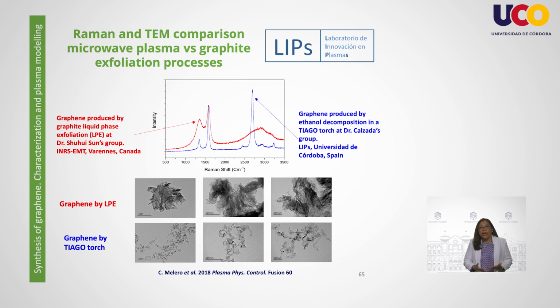Now, in this slide, we can observe the Raman spectrum and TEM analysis of the graphene produced by graphite exfoliation versus the graphene produced from plasma. Graphene from exfoliation presents a higher number of defects and more layers. The morphology is also very different. The graphene from plasma produces flakes with a highly crystalline turbostratic structure and crumpled morphology. This morphology is thought to be important for electron transport and therefore energy storage.